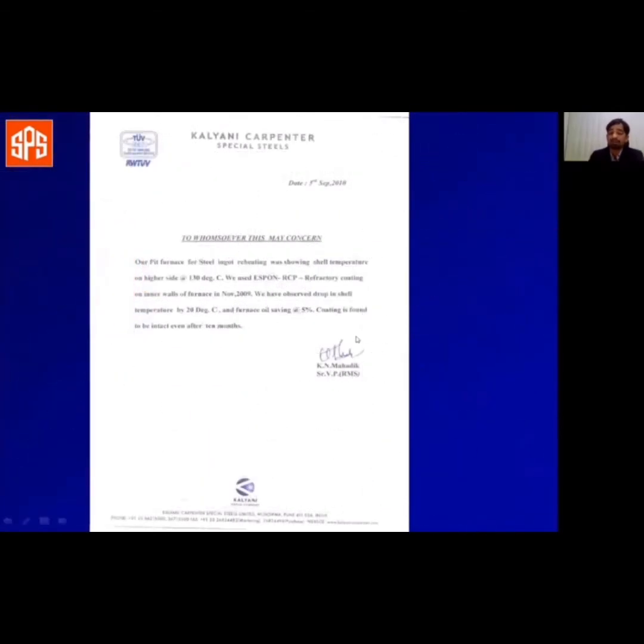At Kalyani Carpenter Special Steel, now Sarloha, located in Mundwa, Pune, the problem faced in their ingot soaking pit was very high temperature of the furnace outer shell. It shows 130 degrees Celsius, and the only problem that they faced were workmen were finding it very difficult to move about the furnace. They were not concerned about refractory lining life or fuel consumption or whatsoever. They just wanted their workmen to be more comfortable around the furnace.